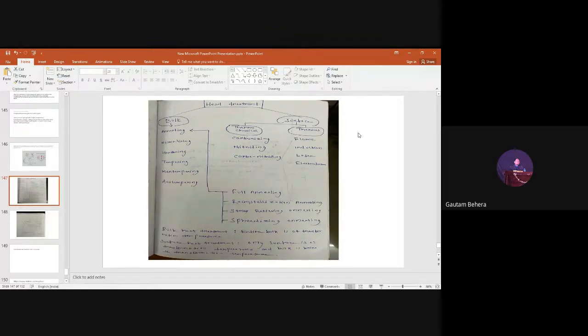So the entire bulk of the steel will be at the transformation temperature. But what is surface heat treatment? Surface heat treatment is only the surface, not the inside or the core. Only the case, or only the surface, will be at transformation temperature. That's why it is called surface heat treatment. It may be 1 mm or 2 mm from the surface, but it is not that the entire bulk will be at the austenitizing or soaking temperature. So that is the difference between bulk and surface heat treatment.